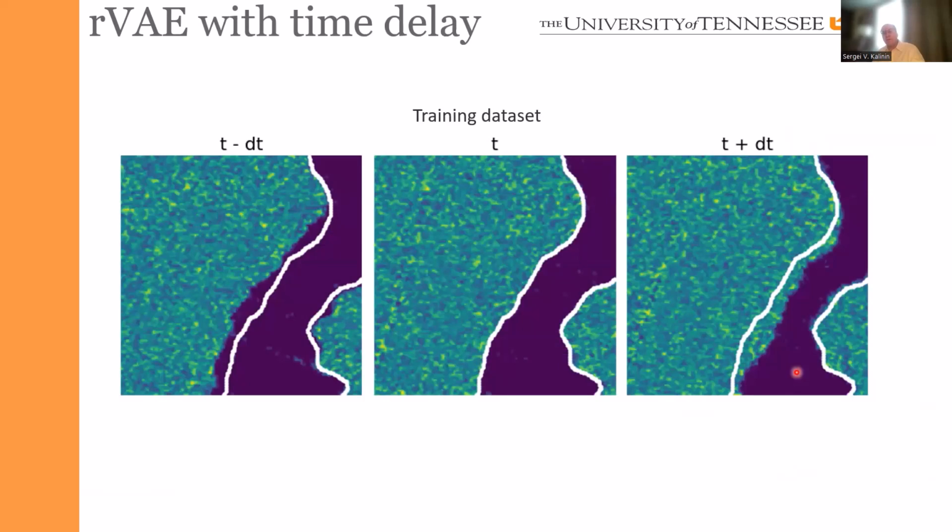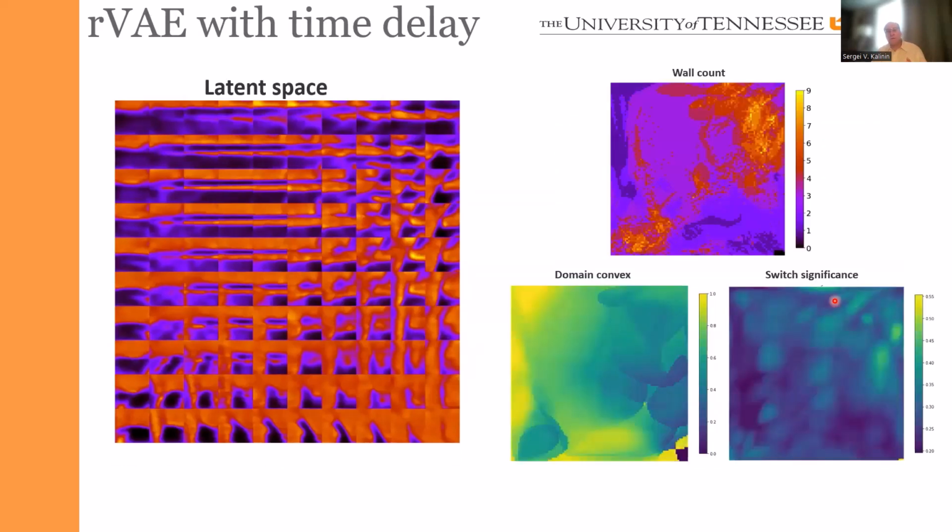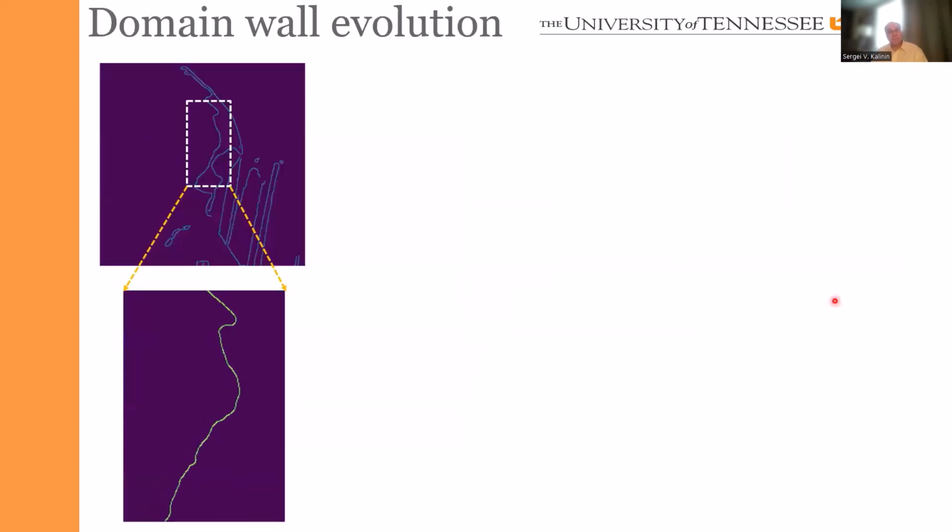So with this logic, for example, it's very easy to extend this analysis to probe the time dynamics. In this case, all we have to do is to choose the position of the domain wall at one time and create our descriptor at time plus delta t. Then we encode the information of the domain dynamics, and we can analyze it, explore it in different ways, and get similar types of insights.